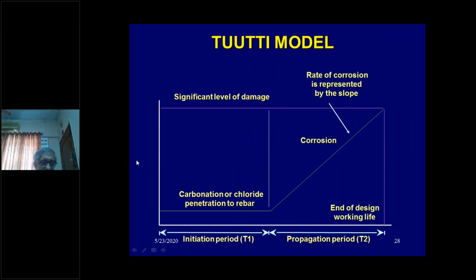Now we just go through this Tuutti model. It was developed by Tuutti. I don't know the year in which he developed it, but you can see here there is an initiation period T1 and there is a propagation period T2. Now what happens is when concrete is born, it is alkaline. Alkalinity in the concrete around the steel does not allow it to corrode. It inhibits corrosion, and therefore when the chlorides or water start penetrating into the concrete, for time T1, no crack